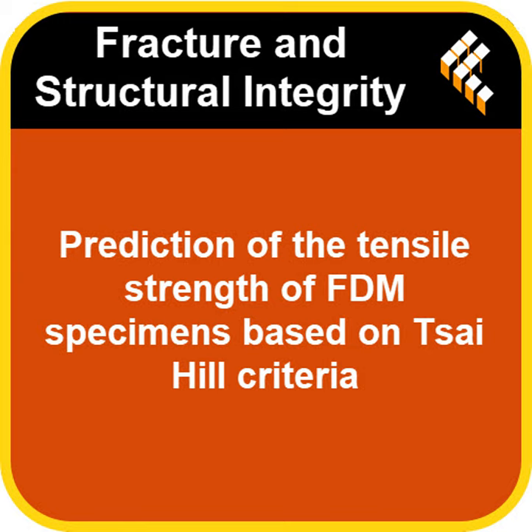Interesting. And did the contour help here? Yes, definitely. In this 45-degree case, that outer contour made a noticeable improvement. It increased both the maximum strength they could handle and how much energy they could absorb before breaking. So it toughened them up. It seems like it. It's likely that the contour helped constrain those angled layers, held them together better, and stopped them from peeling apart quite so easily.